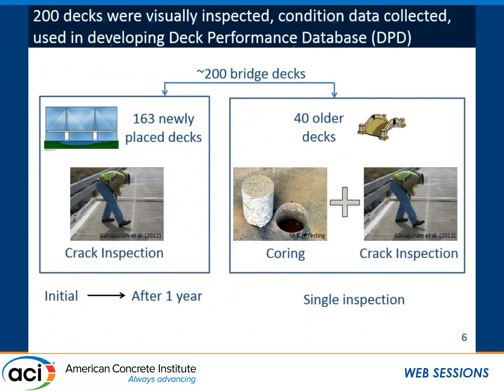So most of these are based on lab work, and what we wanted to do, again, was look at the field data and the actual bridges that PennDOT owned. We looked at a little over 200 bridges, including 163 new bridges, as well as 40 older bridges, and primarily we looked at crack inspections. We mapped the cracks and measured the length of crack per unit surface area of the deck, both at the time of construction as well as 1 year after construction.